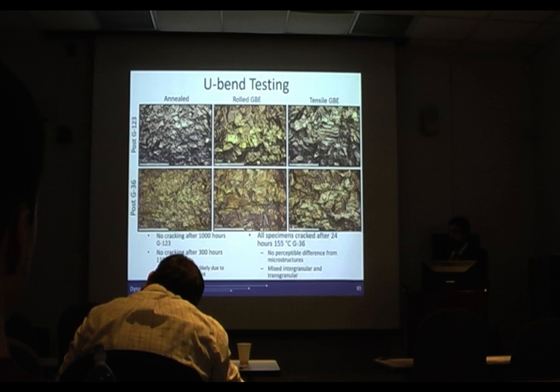We noted strain increased sensitization and desensitization rate, both in the annealed and the rolled GB. But the rolled GB was more resistant. At 1,000 hours, we saw that the tensile GB conversion rate had continued to increase, at a decreasing rate like the others. We had the change in surface roughness. Strain started causing the sigma 3s to corrode. Also, raising the nickel content in 316L greatly increased the IGSCC resistance.